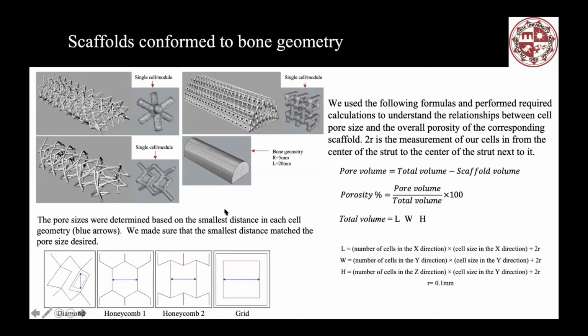So here's the scaffold conforming to the bone geometry. We also design these different shapes of the structure as well. Like here's the pore size, and this is a single cell, and then we generate the semi cylinder to mimic the bone structure. And here is the formula we use to calculate the porosity for each geometry we have. And then here are these 4 different structures. We make sure the smallest distance matches the pore size desired, because different shapes have different geometrical performance. So we just use the smallest distance for each structure.